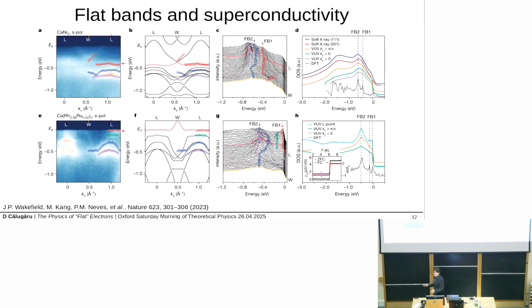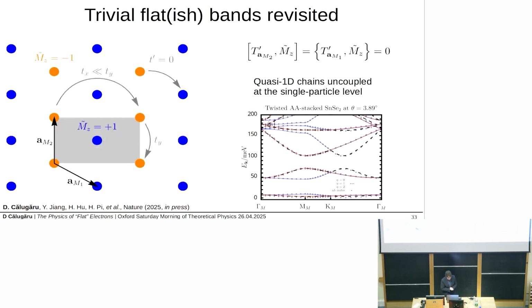Now, I admit that 6 Kelvin, which is the critical temperature of this superconductor, is still not enough. But considering the time scale on which these experiments happen, I would say that it's quite impressive. And before finishing, I just want to say that maybe topologically trivial bands should not be discarded straight away. In fact, in a recent work, we've shown that there's a new, fundamentally different universality class of moire materials, in which the moire potential acts essentially as a magnetic field and realizes a very interesting algebra of the mirror and translation operators.